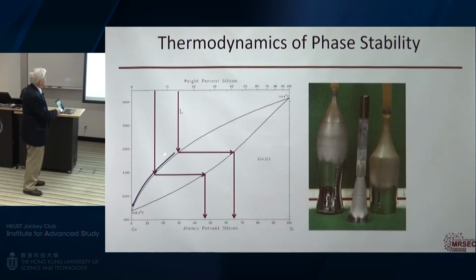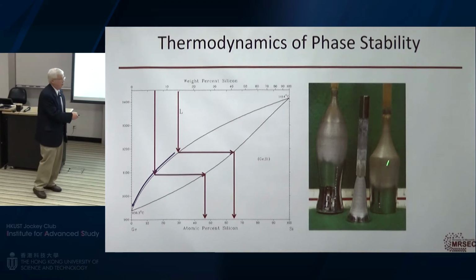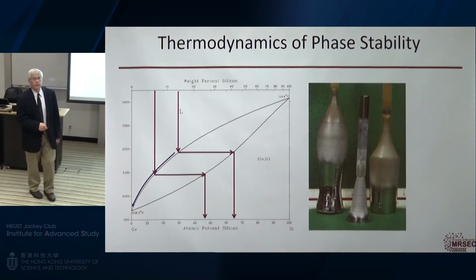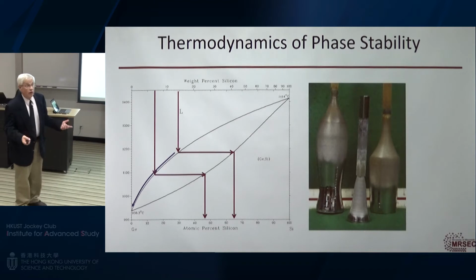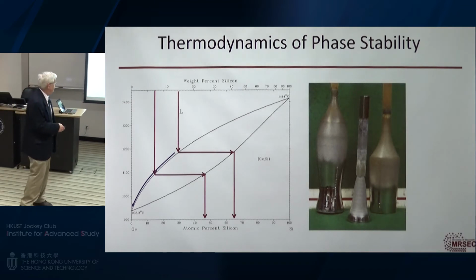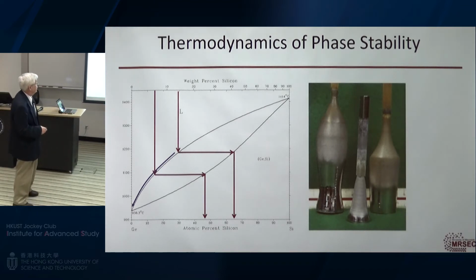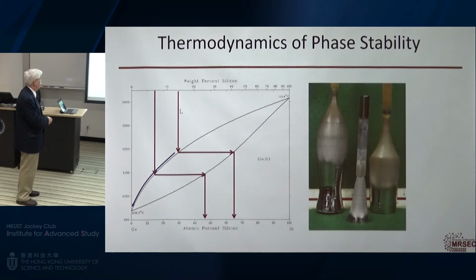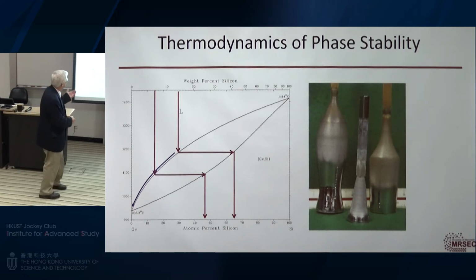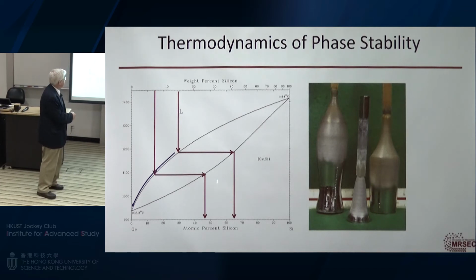That means that I pull more solution out of the liquid, so the liquid shifts composition, and the crystal I'm making shifts composition. And you can see that as it goes from germanium to silicon as I pull the crystal. Now there's ways around this, or people have proposed ways around that by replenishing the amount of silicon in the melt and so forth, but none of those have really been technologically viable. So the fact that I can't use equilibrium techniques to make materials, even in the silicon world, arbitrarily, is why we started to use thin film formation.